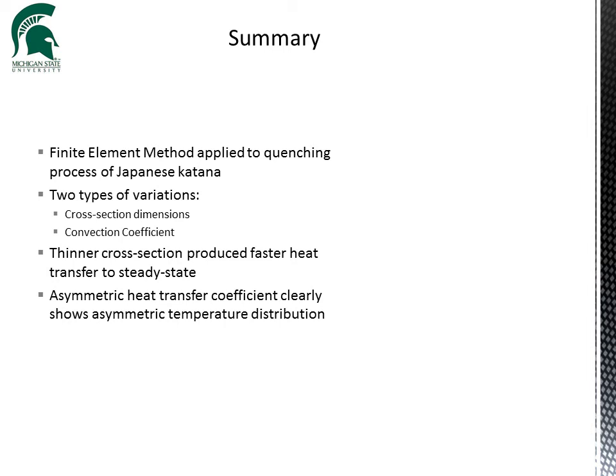And so we performed a FEM study to model the quenching process of a Japanese sword by varying the geometry and convection coefficient, and showed that a thinner cross-section requires much less quenching time, while an asymmetric convection coefficient on the edge induces roughly the same cooling rate as one with a symmetric convection coefficient distribution.